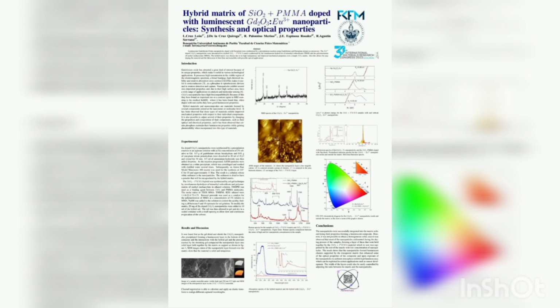The luminescent gadolinium oxide nanoparticles doped with europium were synthesized by the precipitation reaction using gadolinium and europium nitrates as precursors. And these resulting solution nanoparticles were introduced in a hybrid silicon dioxide plus PMMA matrix synthesized by the simultaneous hydrolysis of tetraethyl orthosilicate and the polymerization of the methyl methacrylate.